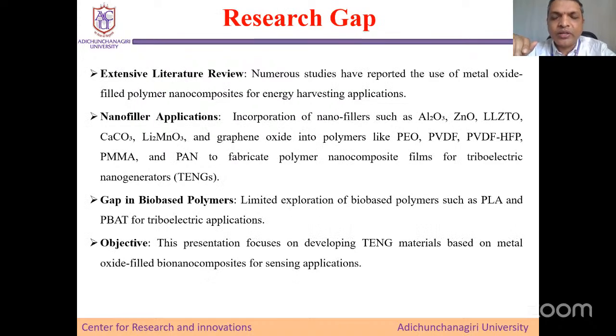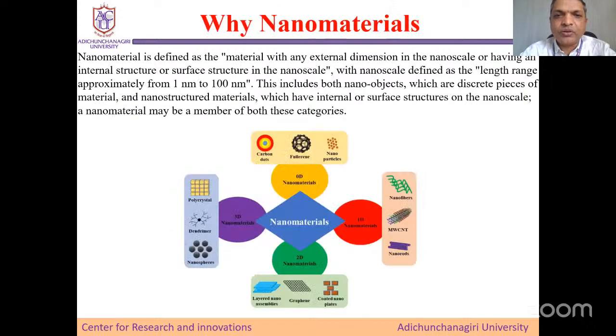So you see here, what is the research gap and what we have done in our work. There is extensive literature reported on polymeric material using metal oxides, and there are some metal oxides which are very effective, of semiconducting nature: aluminum, zinc, calcium carbonate, lithium, LiMnO3, graphene oxide, and so on, using petro-based polymers. There is very limited exploration of bio-based polymers such as polylactic acid and polybutylene adipate terephthalate for triboelectric application. So the present work focuses on the usage of these biodegradable polymers such as polylactic acid or PBAT to fabricate TENG devices.